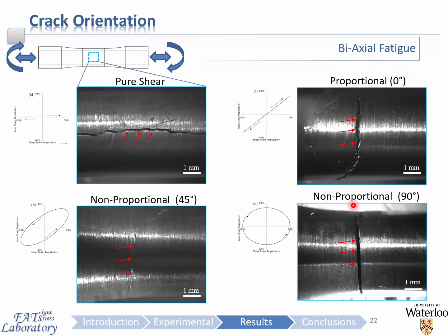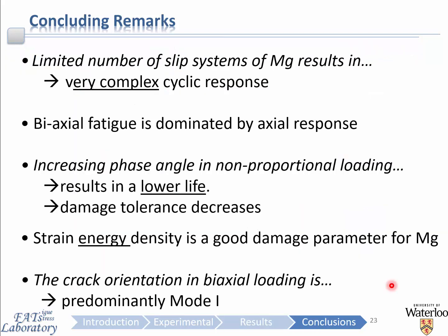Now finally looking at the macroscopic crack orientation, it can be observed that in the pure shear case, the crack initiates on the surface of the sample and then progresses longitudinally along the sample axes. However, for all of the biaxial cases, the cracks still nucleate at the surface, but they progress in a mode 1 opening mode, which is perpendicular to the loading direction illustrated here, here, and here. This supports the previous observation that the axial response and damage is governing the fatigue behavior.